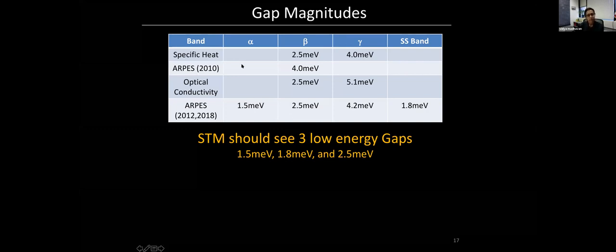And if you take data from specific heat, ARPES, optical conductivity, etc., and you put it all together, basically you find that these two hole pockets are expected to have a gap of approximately 1.5 meV and 2.5 meV. And what I talked about earlier, which is the topological surface state, is expected to have a gap of 1.8 meV. So leaving aside this larger gap, if you look at the energy range between 1 and 3 millivolts, what you should see with STM is actually 3 distinct coherence peaks associated with these 3 bands, 2 of which are the bulk bands, and 1 of which, this one, is the surface state. So let's ask if we actually see this.